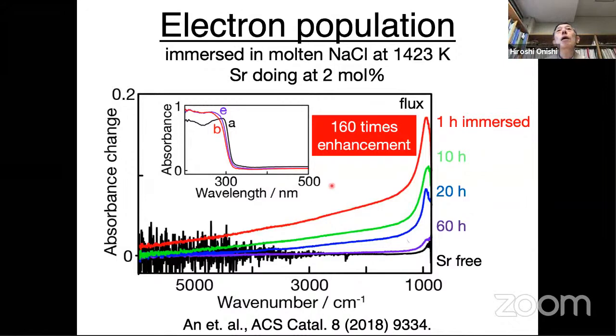In this case, 1400 Kelvin anyway. And we prepared 4 different photocatalysts, 4 different but with one common strontium concentration. We fixed the strontium concentration at 2% and changed how long we heated up the photocatalyst in preparation, from just 1 hour to 60 hours. And we compared the infrared absorption induced by UV light radiation.